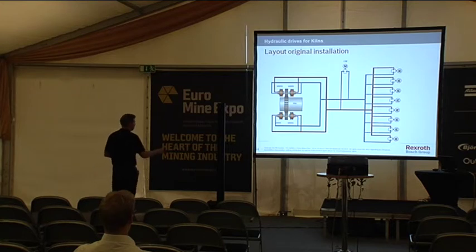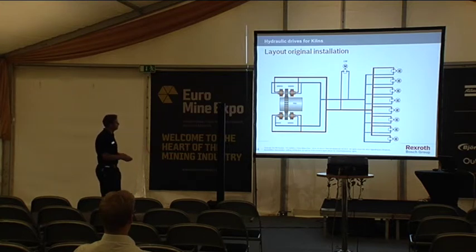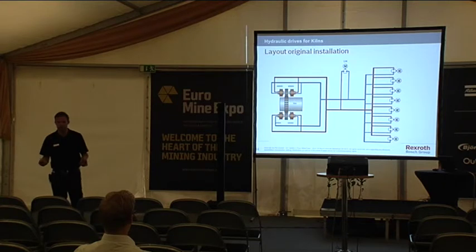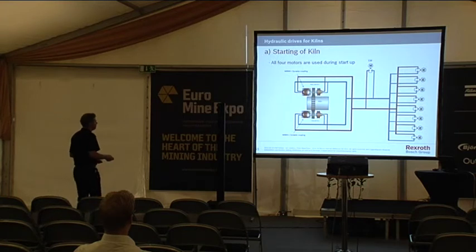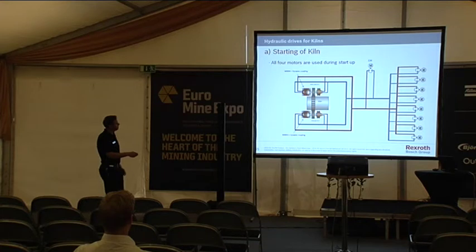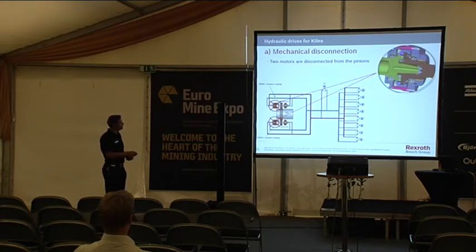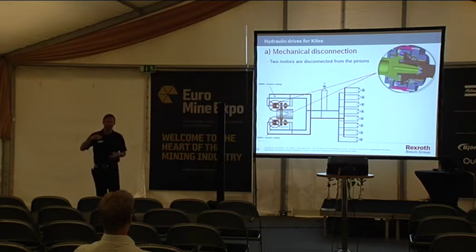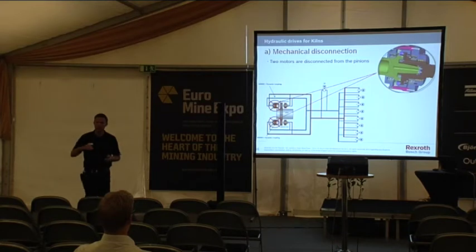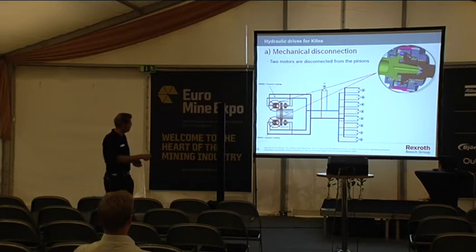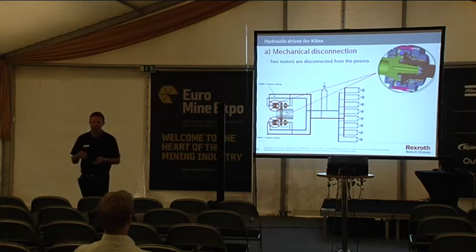Normally you have 4 drive systems for a kiln. It's good because you balance it, you have redundancy, so it's better to have 4 than only 1, for example. It's also better from a mechanical point of view. So with method A, where we have a dynamic coupling, the idea is that we start up the kiln where we need the very high starting torque with all 4 motors, and then we disconnect 2 of them when we have reached a certain speed. And when the torque decreases, then we can disconnect 2 of the motors. And in that way, we can increase the efficiency for these 2 motors since they are optimized for the operating torque.